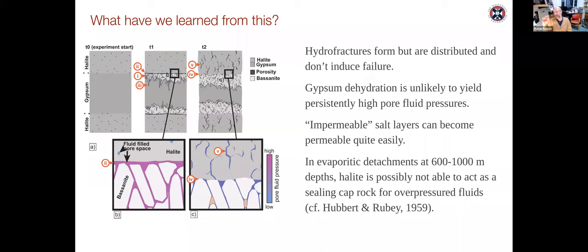Remember, I pointed out that layer of porosity at the interface, that was the stage prior to hydrofracking, when the pore fluid pressure built up there, this scenario here. And with a very high pore fluid pressure, then suddenly it fractured, the fluid fractured its way out of the system and it just drained, right? And if you want to extrapolate that to geological conditions, then you could probably argue that impermeable salt layers are not that impermeable after all. And maybe that at least at the conditions that we had realized in this particular experiment, which correspond to 600 meters to maybe a kilometer down, halite is not such a good sealant as you would expect. Okay.